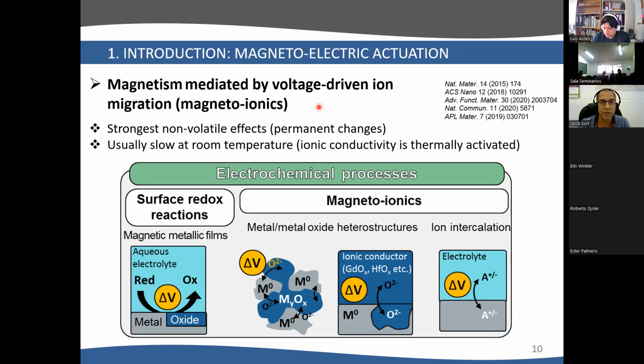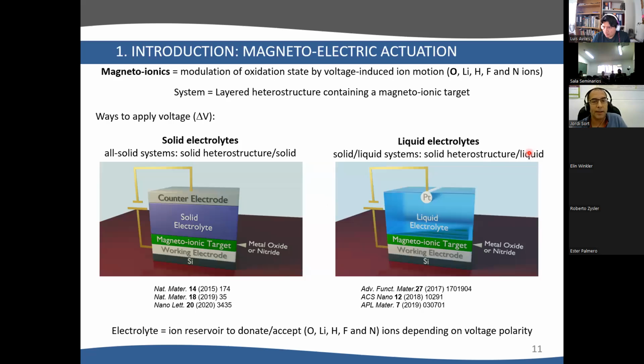It remains after you remove the sample from the electrolyte, but the drawback here is that it's usually very slow at room temperature. Why? Because ionic conductivity is a thermally activated process. Now you can use two types of electrolytes. You can use liquids, as I was explaining, but also solid electrolytes. Here are some papers. You can move different types of ion species, for example, oxygen, lithium, but also people now try to move protons, hydrogen, which is much faster than oxygen, or even nitrogen, as I will show you in the second half of my presentation.